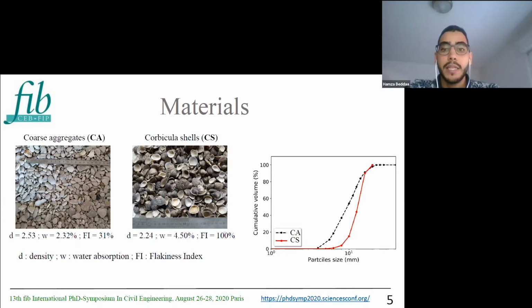Concerning the flakiness index of shells, it reaches the maximum, which is 100%. So this flattened shape of the shells requires more paste volume to cover them, which could affect significantly the concrete properties.